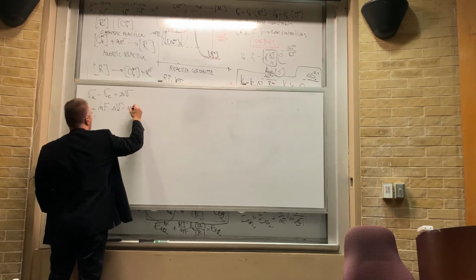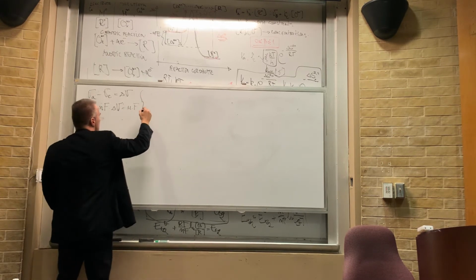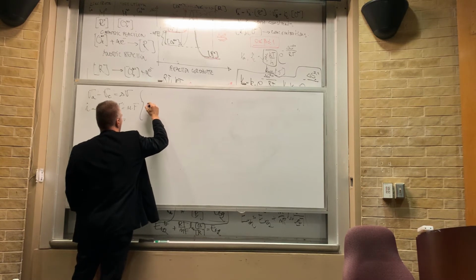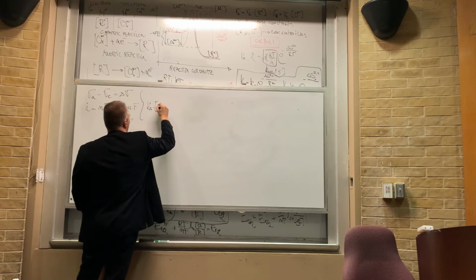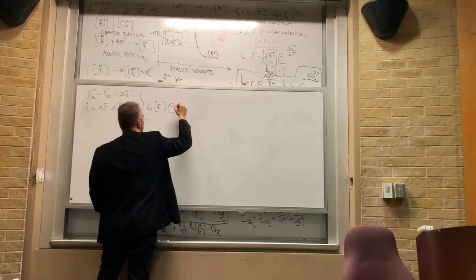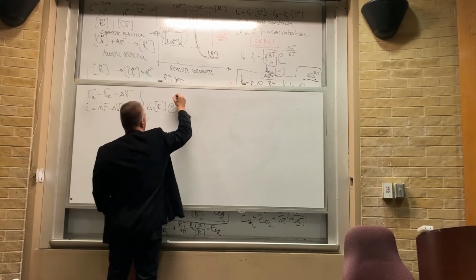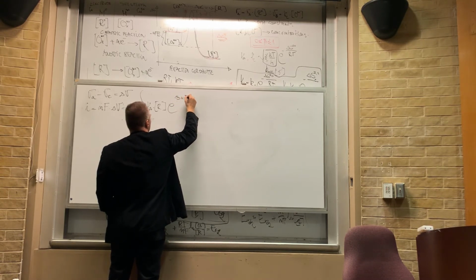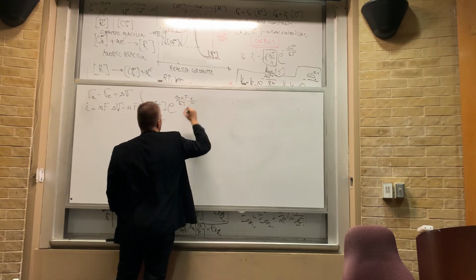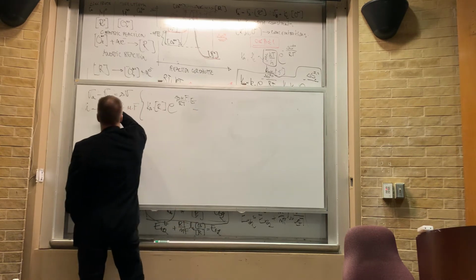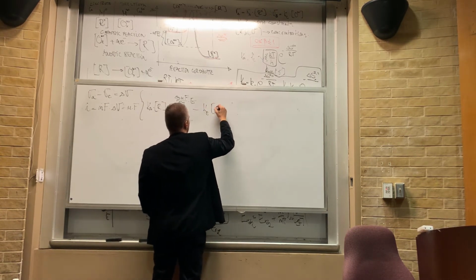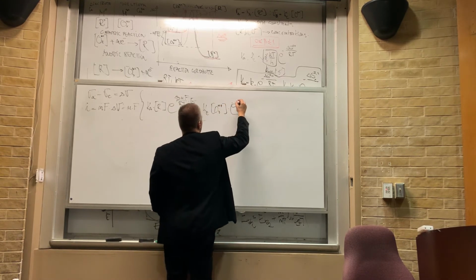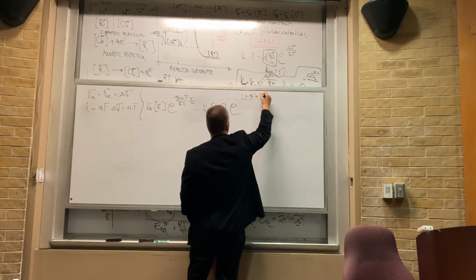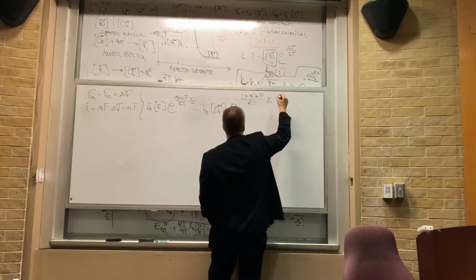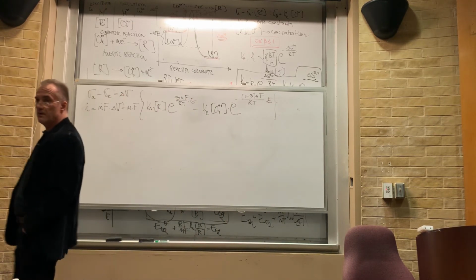And this is equal to F times the difference of the rates. The anodic rate is K anodic times the concentration of the reduced species, e to the beta F over RT times E, minus the cathodic rate, which is Kc times the concentration of the oxidized species, e to the minus (1 minus beta) F over RT times E. Right? Okay.